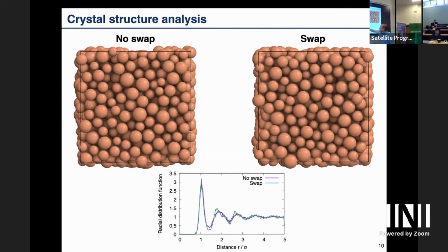And if you also compare no swap, it doesn't look so very different. Wait, what's your sigma? This is a polydispersed system. This is a Gaussian distribution. But then still, what's your sigma? Your distance is normalized by sigma. The x-axis is the distance r in units of sigma, and this goes to 1 at infinite distance. Sigma is the mean radius, so the center of the Gaussian, and that's where the peak is.